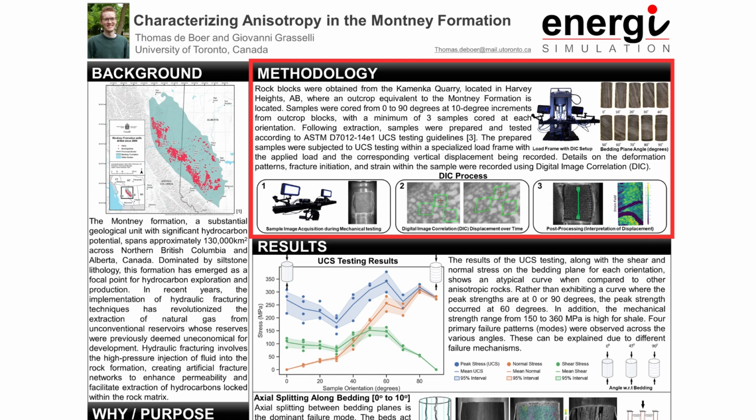Digital image correlation works by taking 2 photos of the sample from 2 different angles multiple times during the testing. The sample is first treated with spray paint to create a speckled surface, and DIC software is able to track that speckled surface and track the displacement of that surface over time. Once the displacement can be tracked, you're able to, in post, calculate the strain across the sample surface.